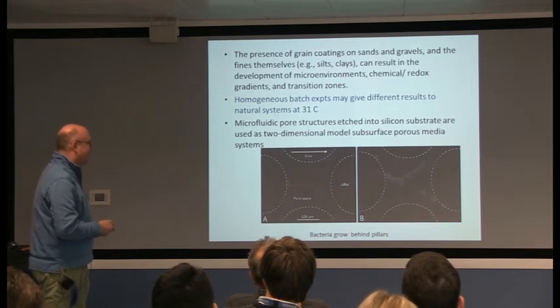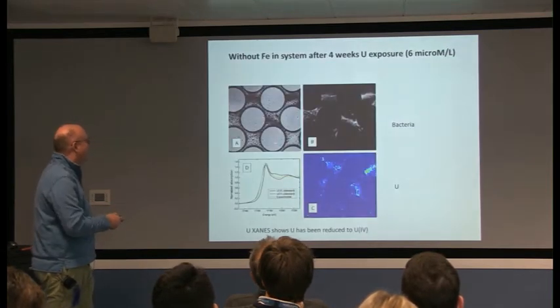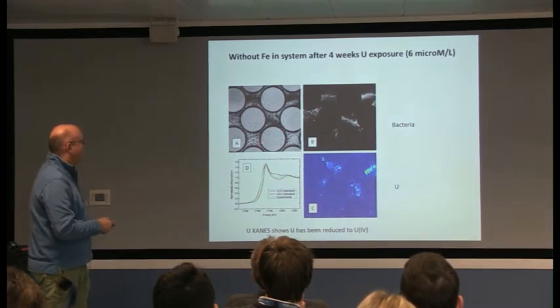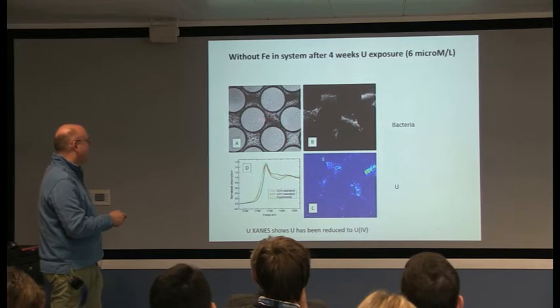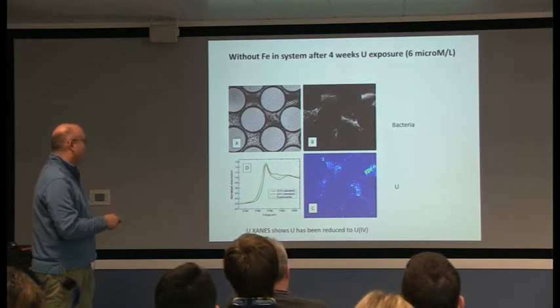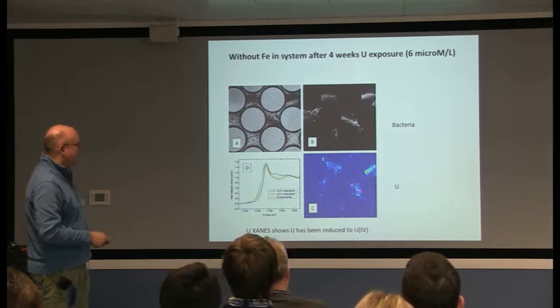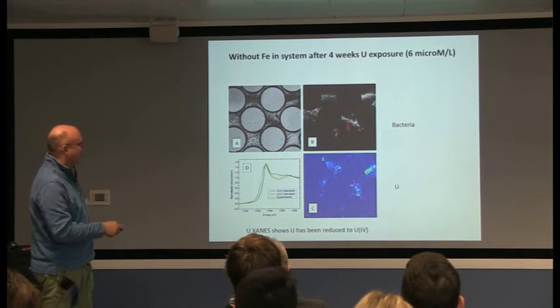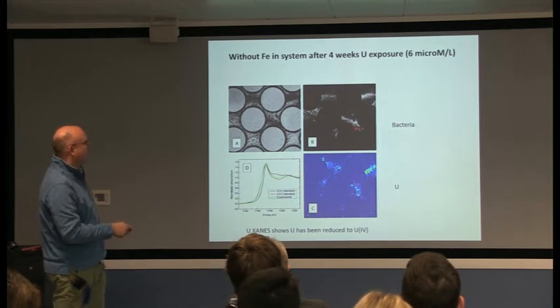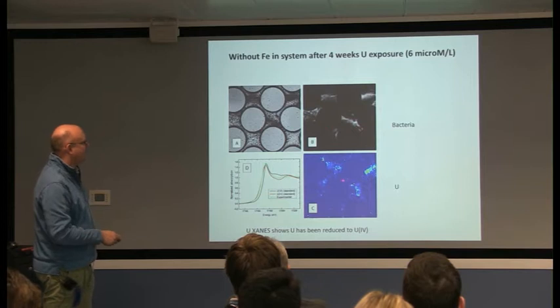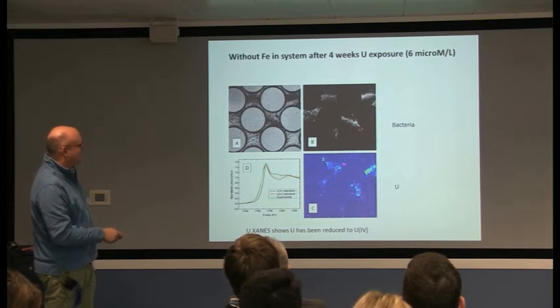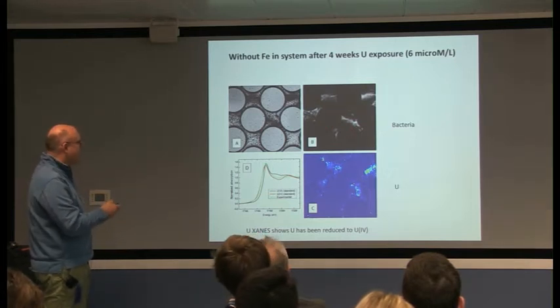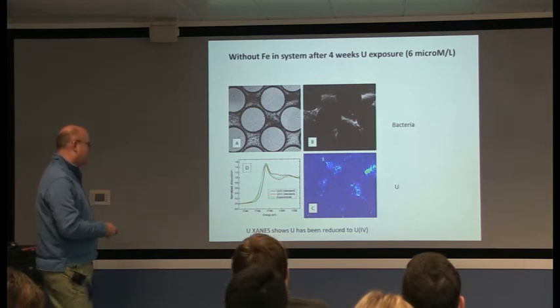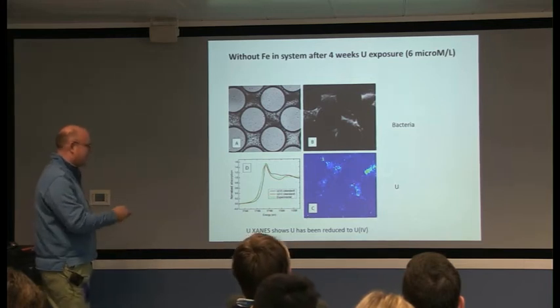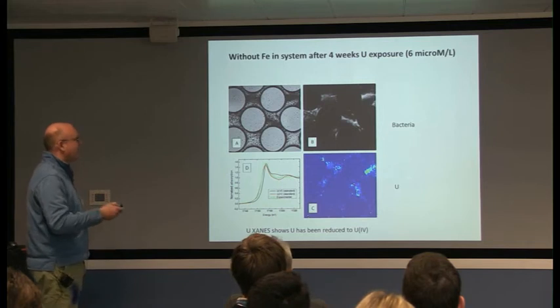So that's fluorescence light microscopy showing the bacteria, and here is an X-ray picture. This is putting some uranium in, so this black is uranium, and you can see that the uranium actually really matches where the bacteria is in the XRF picture. That's the visible light microscope fluorescence image to see the bacteria, and you can see the uranium and bacteria are well resolved, and if you do the microprobe stains, you see the uranium is being reduced to uranium-4.